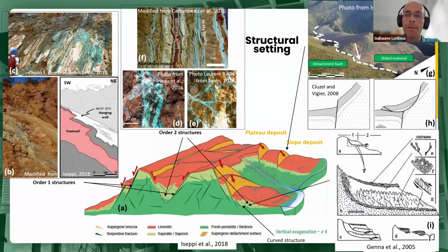Nickel enrichments tend to increase from basin to plateau and slope deposits in relation with the development of thick saprolite profiles, the effect of erosion after uplift, and gravity-driven processes generating structural and topographical traps. More specifically, in slope deposits, channeling, containment, and trapping of the metal-bearing solutions, and feedback between fracturing and weathering, is responsible for producing high-grade concentration.